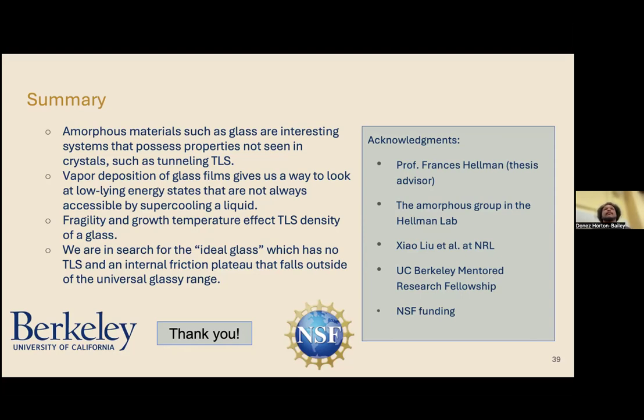Why is it instead of the magnetron sputtering system? Because I think that for magnetron sputtering we have densities, right? Yeah. Well, this is something that I'm actually trying to figure out now with my alumina films. We did do both sputtering and e-beam to compare the two, and from what I've seen, the e-beam films are more dense from measurements, but it turns out that e-beam produces rougher films, so they're not as flat, and so the density has very large error bars and is not as reliable. But typically for most materials that we've seen, sputtering should give you a denser film just because it's a more energetic process. You're hitting it with larger ions than just electrons. But yeah, that's kind of it.